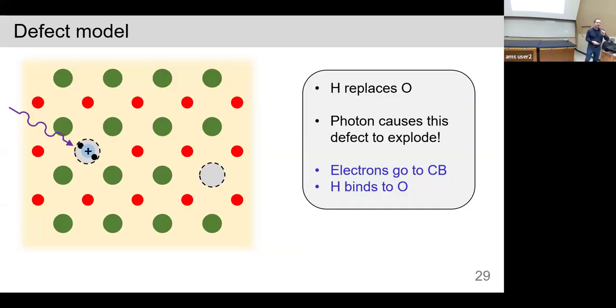So we come in with a photon, and what happens? It causes the defect to explode. What I mean is everything leaves. So the 2 electrons leave, the proton leaves, and the electrons go into the conduction band. In essence, they're free to conduct electricity. So that's where you get the reduction in resistivity or increase in conductivity. And the hydrogen, the proton leaves too, and it binds to some oxygen atom in the crystal. We're not sure exactly where, but that bond is strong enough so that at room temperature, it's metastable and it will last. It'll stay there for a long time. So we think the hydrogen is the key ingredient to make this very, very persistent.